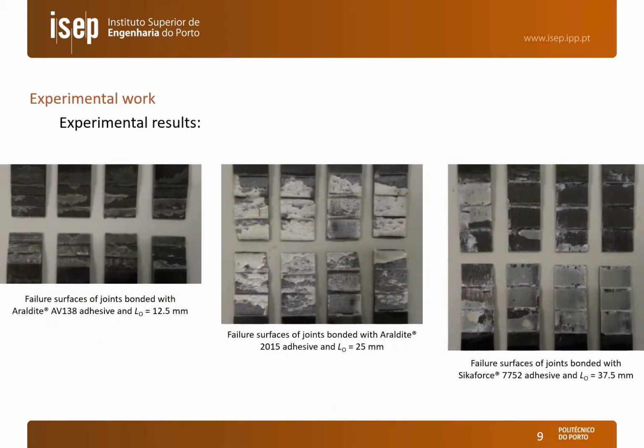Regarding the results, we begin by showing the failure modes, one figure for each adhesive and just one example of an overlap length. We can see that failures were mostly cohesive in the adhesive layer, but in some of the conditions we had also concurrently interlaminar failure of the composite. But mainly failure of the joints took place by cohesive failure of the adhesive.